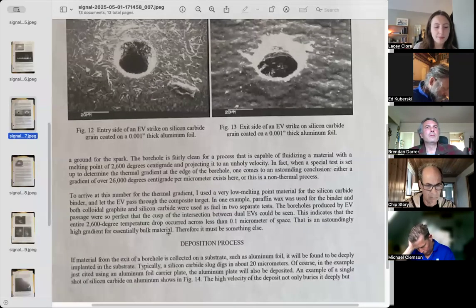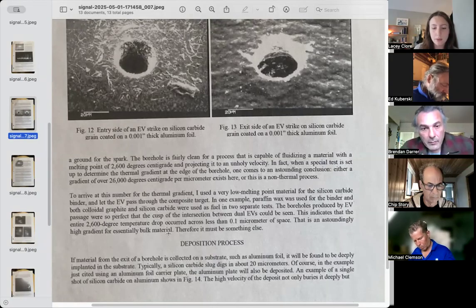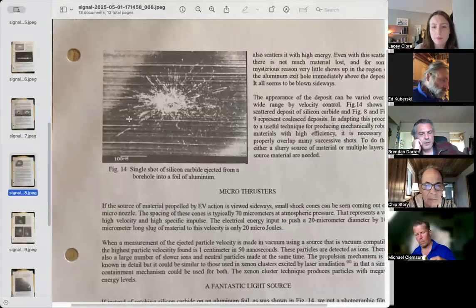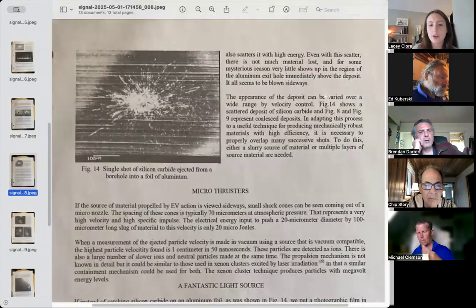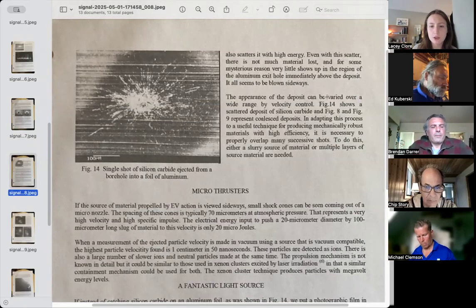Deposition process. If material from the exit of a borehole is collected on a substrate, such as aluminum foil, it will be found to be deeply implanted in the substrate. Typically, a silicon carbide slug digs in about 20 micrometers. Of course, in the example just cited using an aluminum foil carrier plate, the aluminum will also be deposited. An example of a single shot of silicon carbide on aluminum is shown in Figure 14. The high velocity of the deposit not only buries it deeply, but also scatters it with high energy. Even with this scatter, there's not much material lost, and for some mysterious reason, very little shows up in the region of the aluminum exit hole immediately above the deposit. It all seems to be blown sideways.